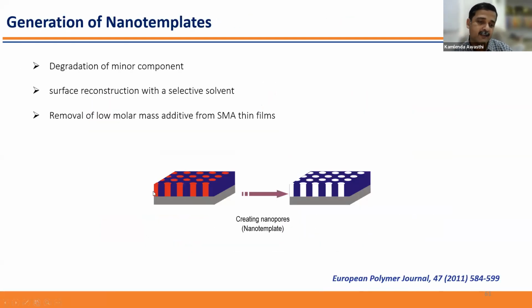Here you can see there are two polymers, polymer A and polymer B. Polymer A is represented by red and blue. What is happening is that the red polymer A reacts with the additive, and later on we can remove this additive with ethanol, methanol and so on. So this part goes away, and the white here basically denotes the porous channel that is available, an ordered porous channel. Here we can maintain the ordering, and we can even maintain the porosity while changing different molecular weights.